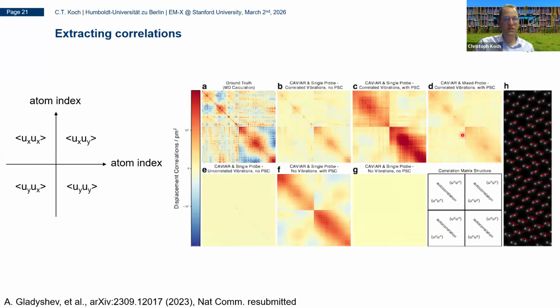So what we can do now is give numbers to each atom and number them and plot now a plot like this, where we plot all the atomic numbers in one dimension and also in the other direction, and now see correlations between them. So we have now the displacements in the x direction and the displacement in the y direction correlated with one another. And of course, for x and y, we always see along the diagonal that they're fully correlated. So that's why we expect a line for the x and the y displacements. We also have the xy and yx displacements, which of course are expected to be mirrored. And we only plot the expectation value here, basically averaging over all the different